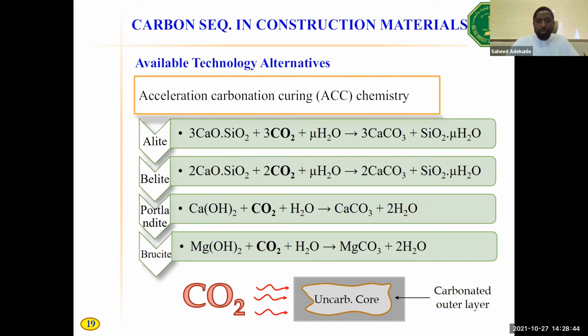Just picking up from the last question which you raised, it's been reported widely in the literature. Some scientists have actually come up with the stoichiometry of carbon utilization in cement. And there is a very clear stoichiometry where we can calculate the theoretical carbon uptake, okay? But remember that the theoretical uptake is a limiting level which we cannot achieve practically, because as you can see on the screen, when you react CO2 with the outer shell, the outer shell becomes denser and it will make further penetration more difficult for CO2. So that will not be able to attain the theoretical limiting level.